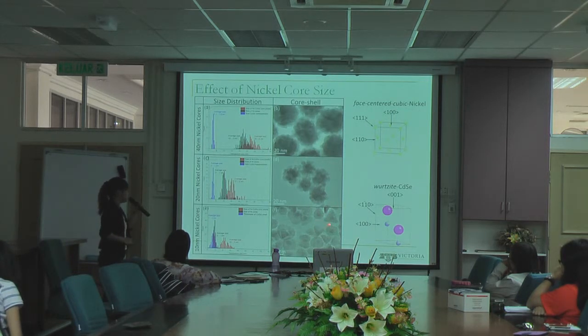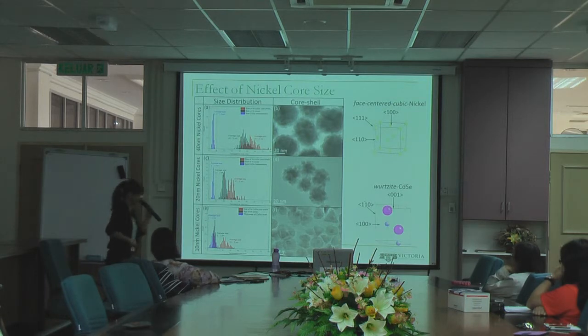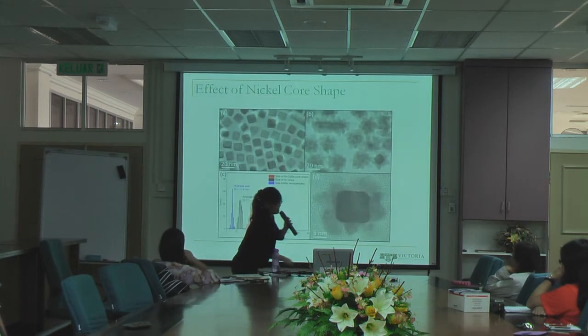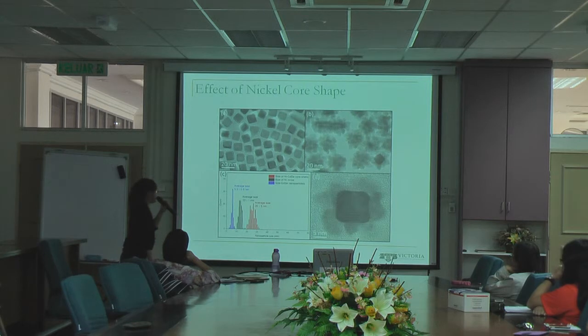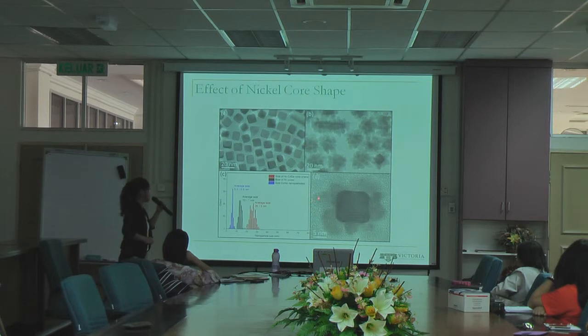So we can consider that cadmium selenide is essentially growing on nickel as if it is an amorphous material. So lattice mismatch, we expect, does not play a very strong role here at all. That's why cadmium selenide can grow into a very large size domain, and also it fully encapsulates the surface of the nickel cores. And it's quite a similar case for the cube-shaped nanoparticles. It's also due to the large lattice mismatch that in this case the cadmium selenide domains grow onto nickel with small contact area as well as small size.